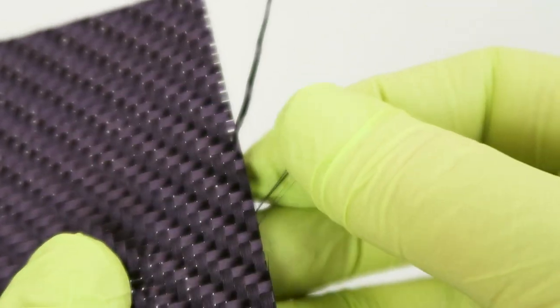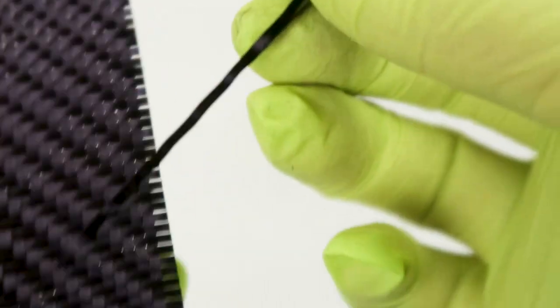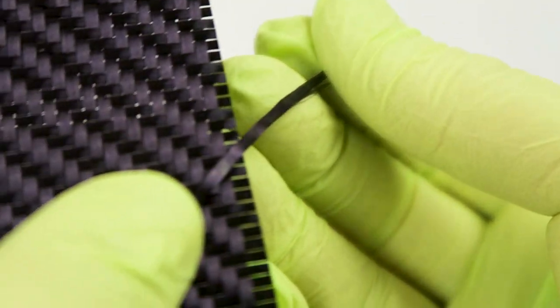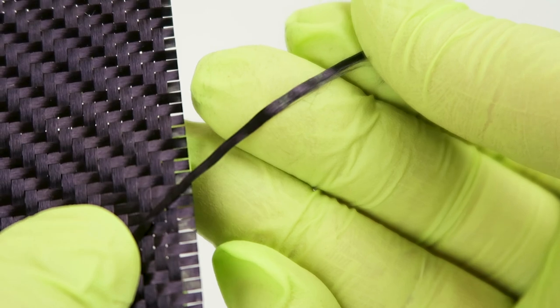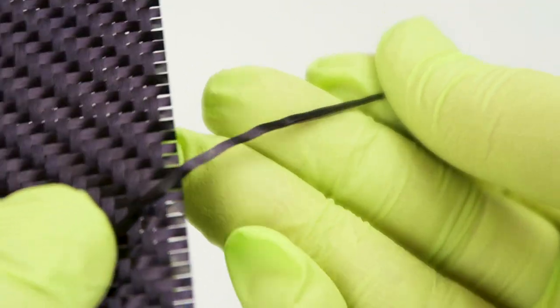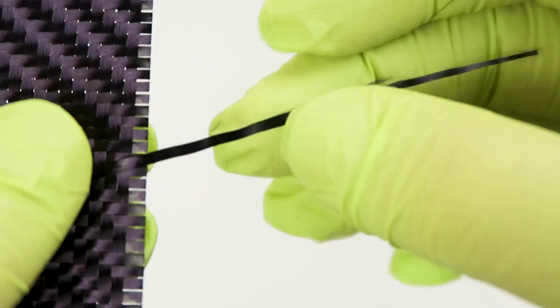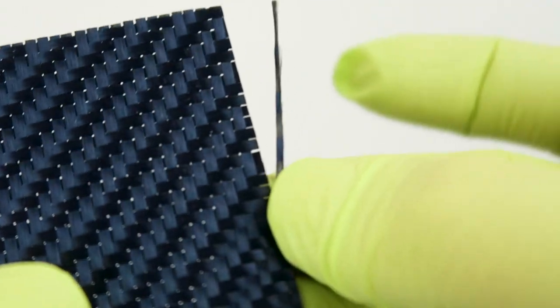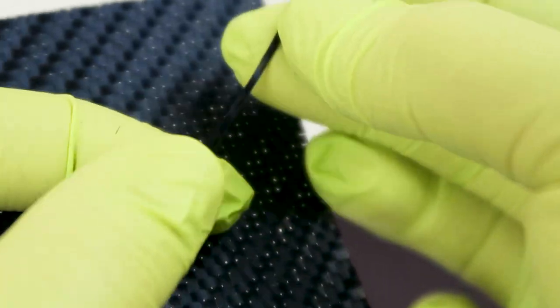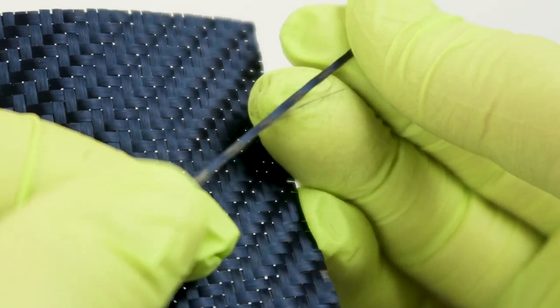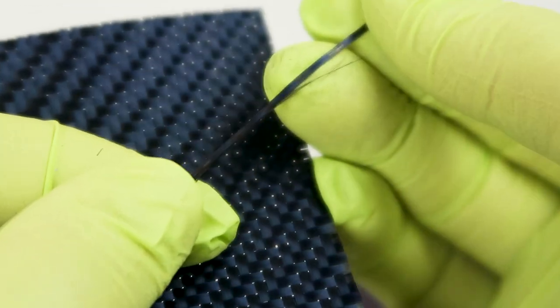The other important element to note here is that the colorant is added after the fabric has been woven. As you can see when you remove a piece of the tow, there is a difference in where it was weaving around the other piece. There is some of the black carbon fiber showing through. So if you were to distort the weave enough to reveal that, that could also ruin your cosmetic finish. It's just another point to note when working with the fabric.